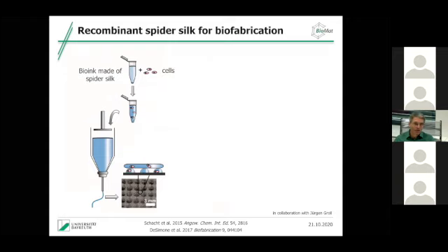So especially with the cardiomyocytes, I've shown you before, they're not migrating. So if we just would put the cardiomyocytes on top of such a scaffold, they will never enter it. They just will sit on top. So therefore, we had to actually overthink that kind of story. And the idea was very simple. Well, if we just place the cells together with the materials in the scaffold, that would be the best option. And this is what is called biofabrication, the simultaneous printing of the hydrogel with the cells. So we mix the cells with our spider silk ink, and then we actually print that together. And all of a sudden, the cells are in place. They don't have to migrate anymore.